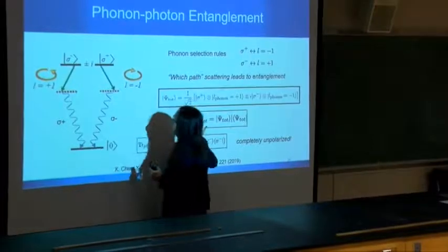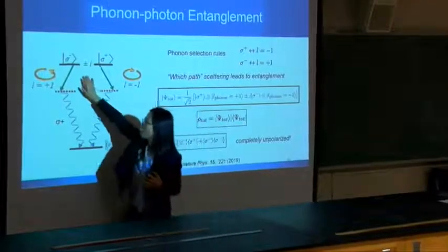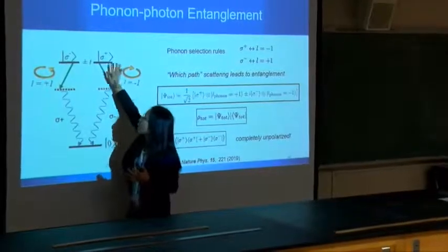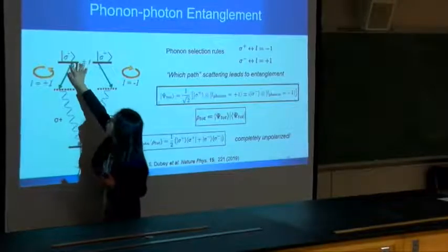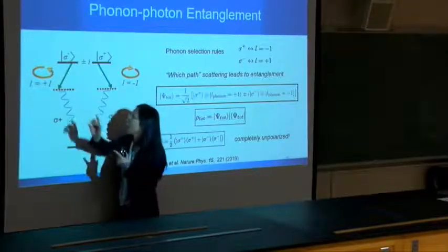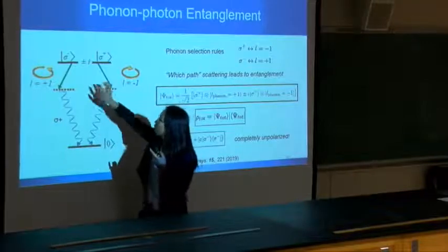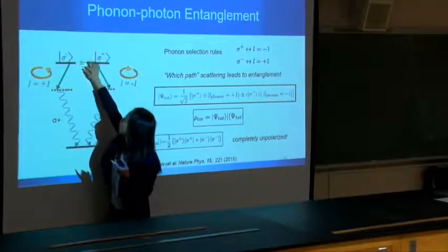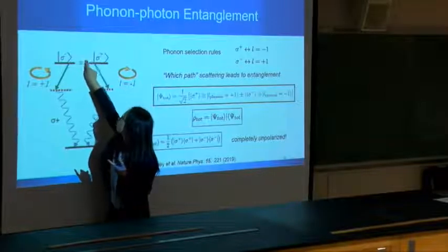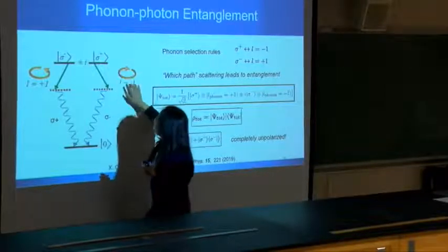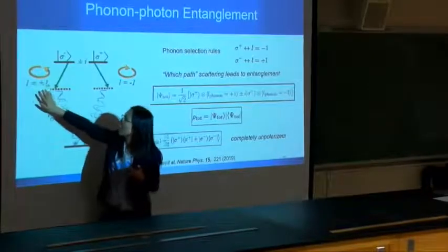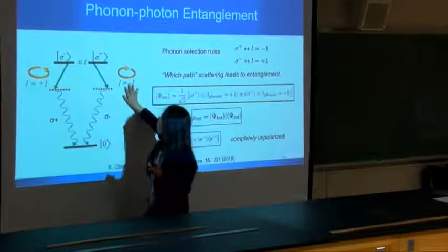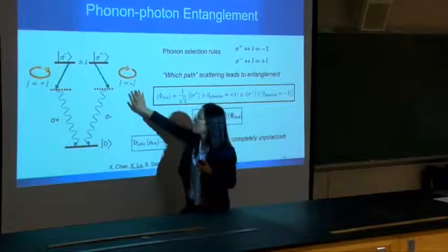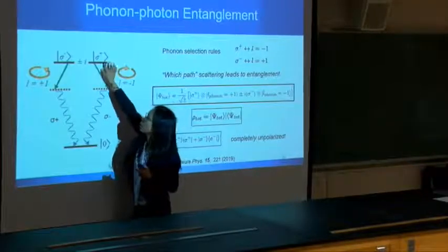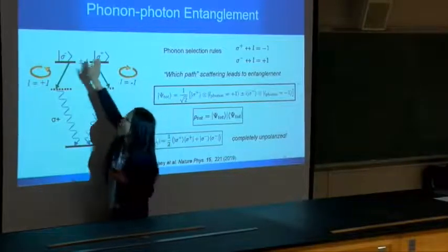The unpolarized emission is mainly because we have two indistinguishable paths. From the neutral exciton, we have sigma minus and sigma plus, and then they split into two peaks with linearly polarized light at a 90 degree axis. So here we put a plus minus i. And the phonon has angular momentum like plus one, minus one. Due to the phonon selection rule, minus one phonon can only talk to sigma plus photon. It will not interact here.